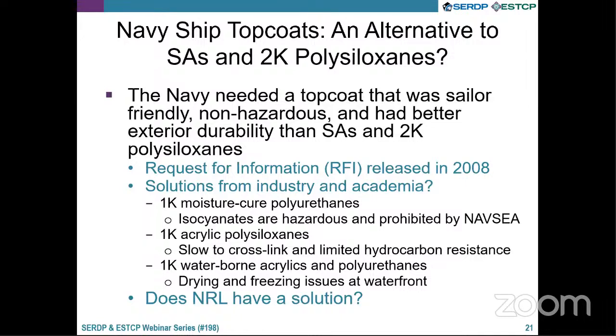There were some who proposed single-component acrylic polysiloxanes. Again, one of the main problems with this technology is that it's slow to cross-link, offers limited hydrocarbon resistance, and can be higher in VOCs for some formulations—that's as a high-gloss clear. So you can imagine if you have to add fillers and so on to reduce it down to a semi-gloss finish, you're going to have an even higher VOC content within that coating.